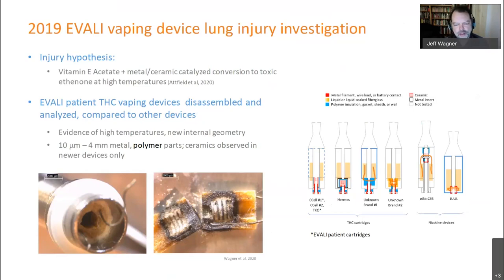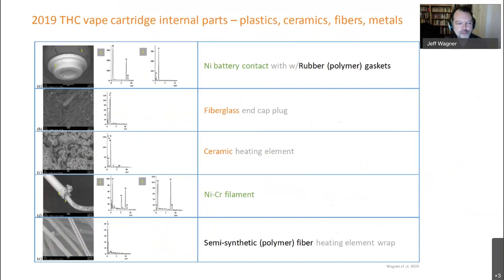That became then another area of interest in this study because those polymer parts are exposed to high temperatures as well, potentially. And in the image on the lower right, you kind of see a schematic of the different part configurations we found in the study. And the blue regions are all the polymer-based components. And those range up to 4 millimeters, but down to 10 microns in some cases. The smallest ones would be, well, I'll show you that in the next slide. So this is an example of an inventory of the different components in just one of the more modern THC delivery devices, in which we found plastics, ceramics, fibers, and heavy metals.